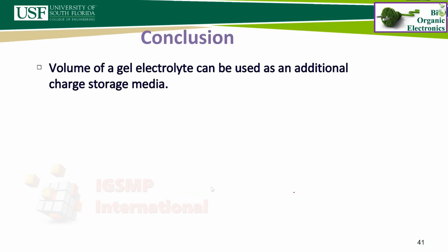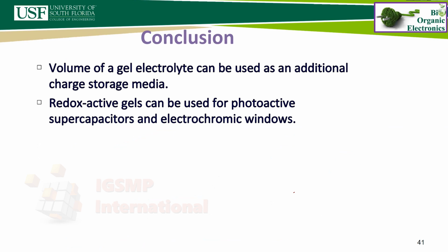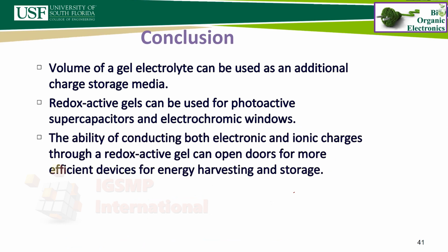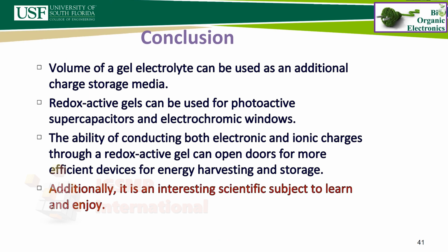So just to conclude, we learned that we can use the volume of the gel electrolyte as additional charge storage media for supercapacitor applications. And using redox active gels, we can have photoactive supercapacitors and electrochromic windows. We can use this balance between the electronic and ionic charge transport property of the gel for energy storage and harvesting. But more importantly, for me and the students who are working on this, it is a very complex research subject that we enjoy doing, with different types of material characterization, device optimization, characterization, and so on.